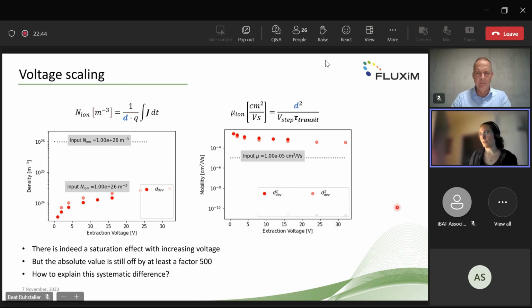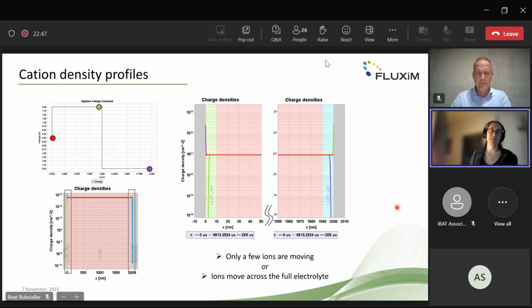And now, thanks to the simulation, we can also have a look inside the device. So here you can see the applied voltage, and for 3 different points in time, we plot the charge density profile, or rather just the ion density profile. And you can see here that this is like the full profile, and here is a zoom in region on the right-hand side. You can basically see that there is only a little small fraction of these charges that accumulate at the electrodes, and a lot of these charges did not move away from their steady state constant distribution.